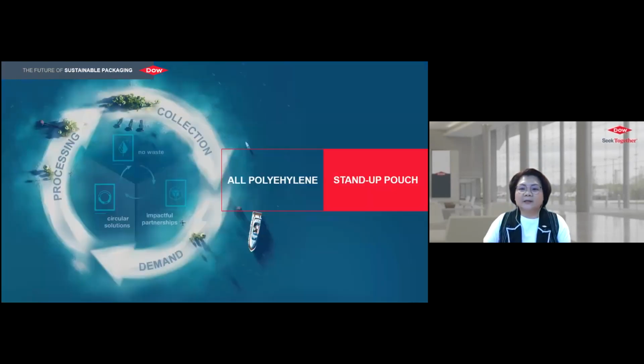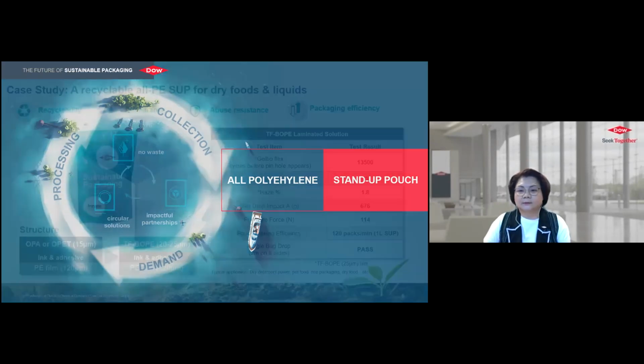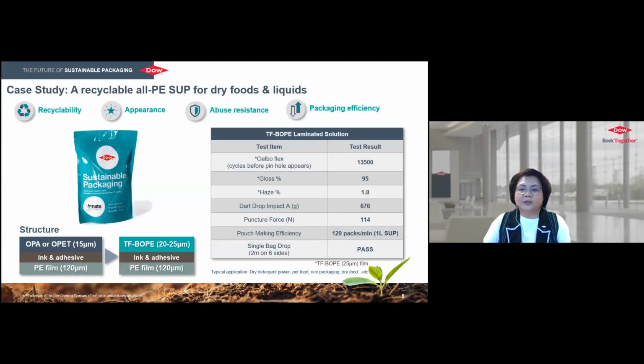So the first packaging format we are going to look at is the polyethylene stand-up pouch. Here is a case of TFBOPE-based stand-up pouch development. TFBOPE replaces BOPA, providing functionalities such as printing web, toughness enhancement, and etc. TFBOPE laminated solution demonstrates outstanding performance such as pinhole resistance, impact and puncture resistance, make it fits well for dry products and liquid SUP. One key thing to take note is that the barrier performance will not be as good as those using BOPA or BOPET due to the reduction in oxygen barrier performance.